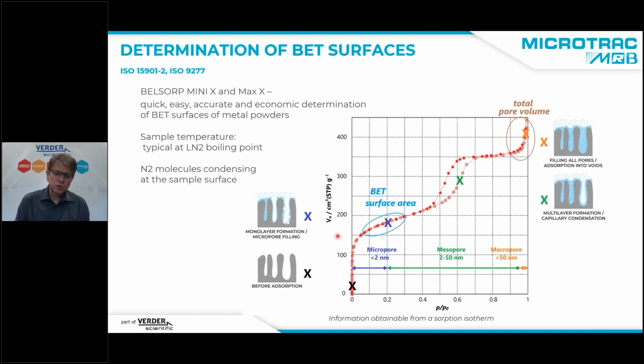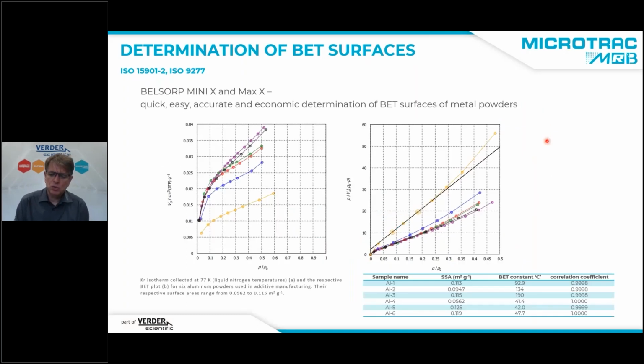Basically, what happens is you cool the sample to the temperature of liquid nitrogen. Then nitrogen molecules are let into the chamber, and these nitrogen molecules are condensing on the surface of our sample, because it's the temperature where they freeze, basically. And then the surface is covered slowly but surely by these nitrogen molecules. So when we let in few molecules, a small area is covered. When we let in more molecules, then the coverage of the surface becomes larger and larger, and also the smaller and larger pores finally are filled with the nitrogen molecules. And from this, we can calculate the surface area.